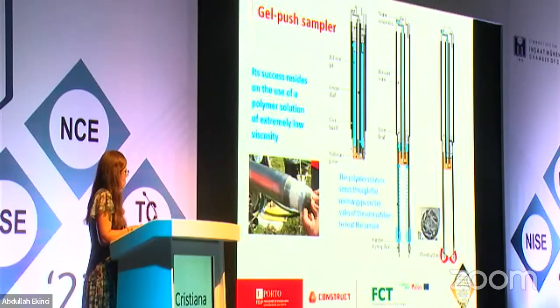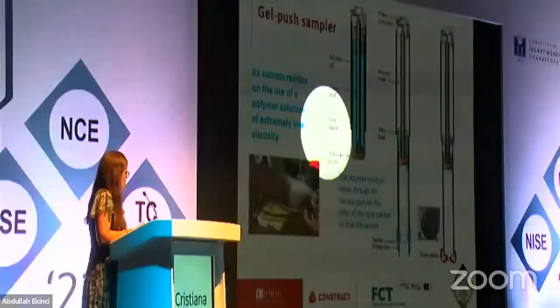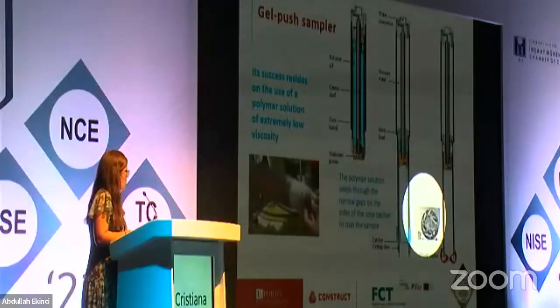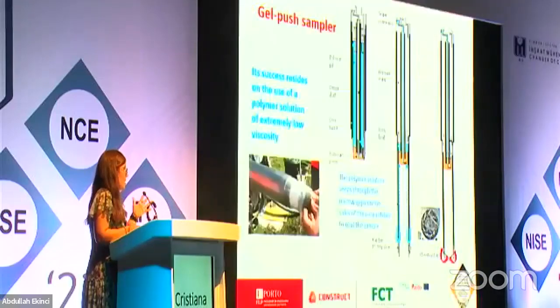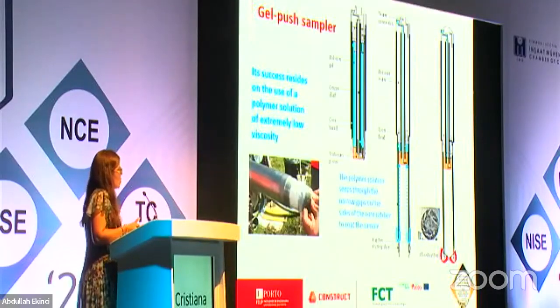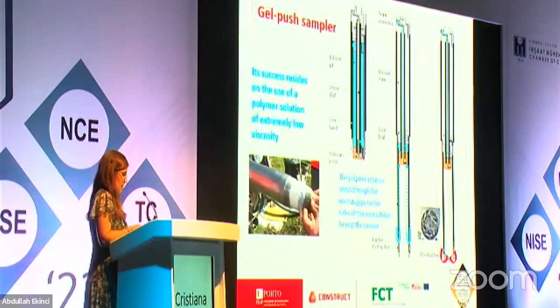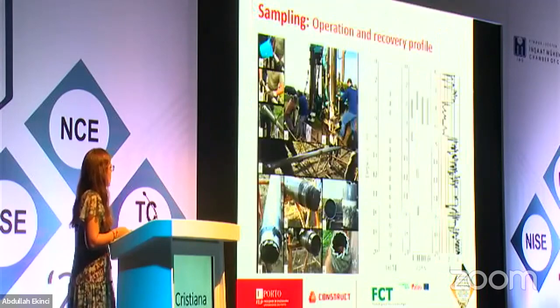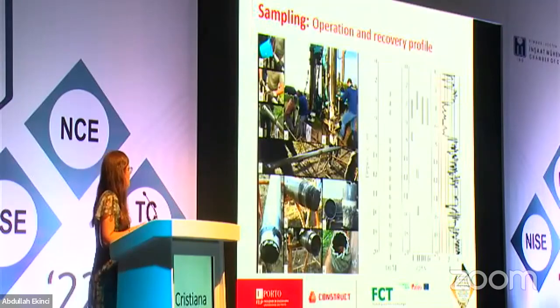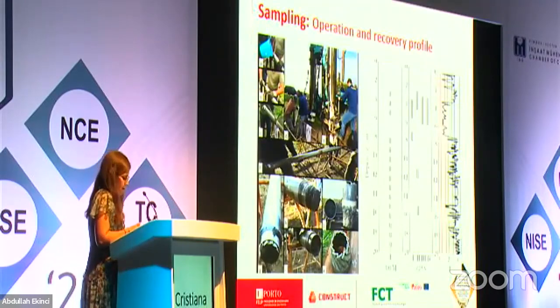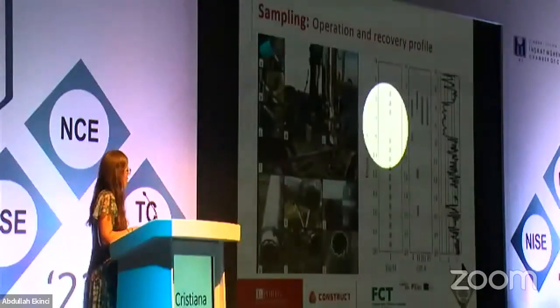And at the end, so after sampling, you can see here the core catcher, which is closed. So it initially was open, so we didn't see it. And at the end, it closes with some metallic pressure that's applied at the end. So it makes sure that you can collect the sample and bring it to the surface. Just a few pictures of the process. And we have here the example of how many samples and at which depth we collected them.